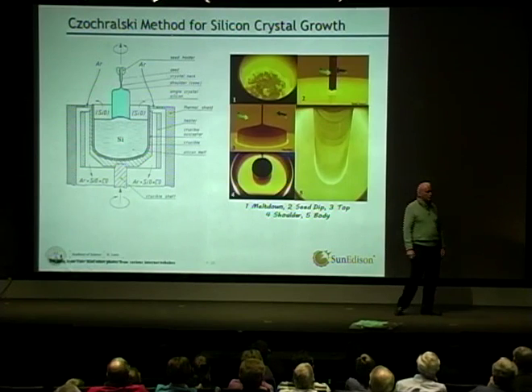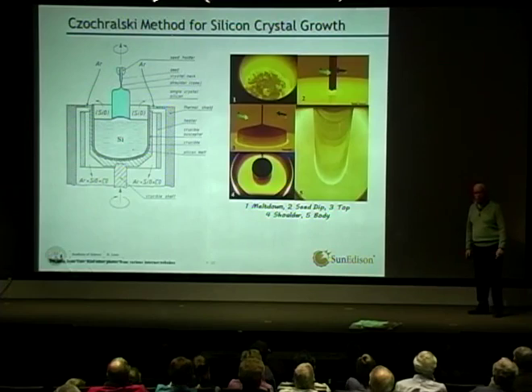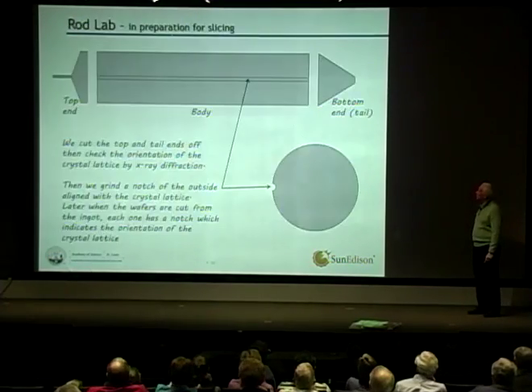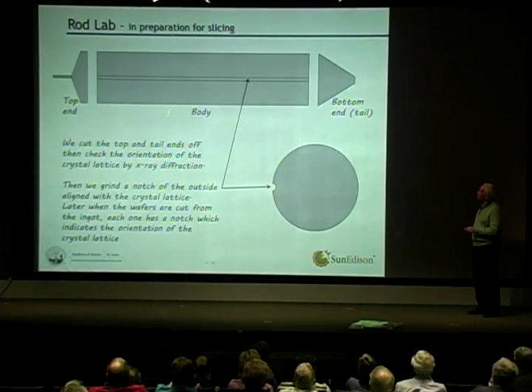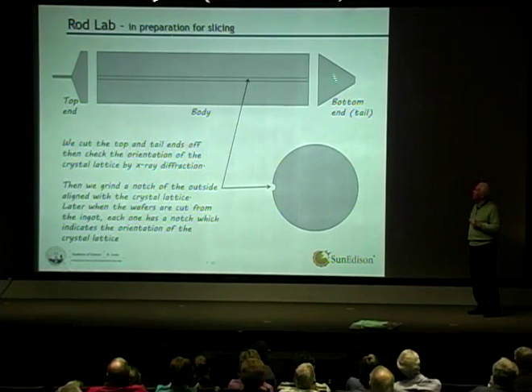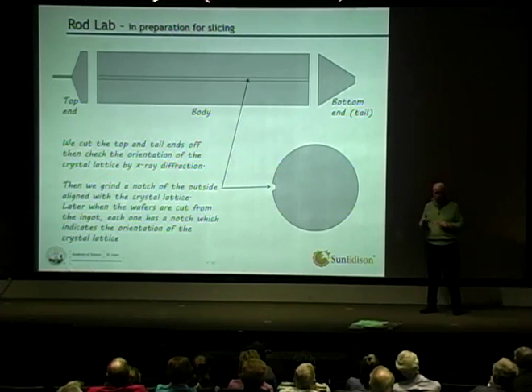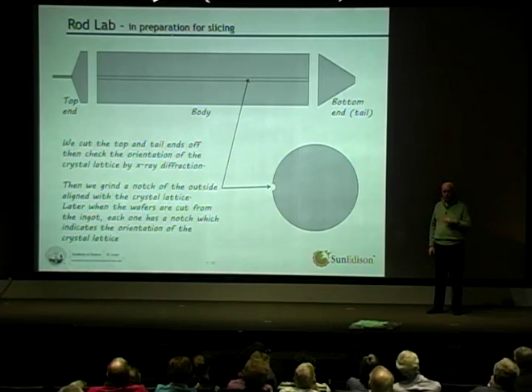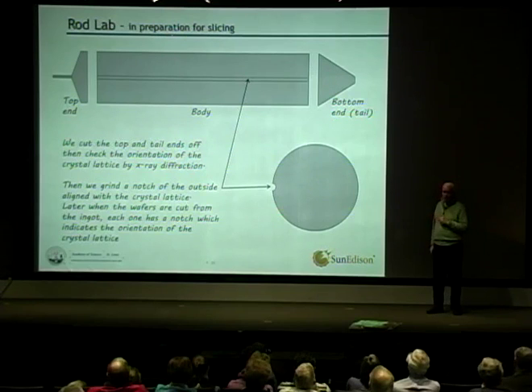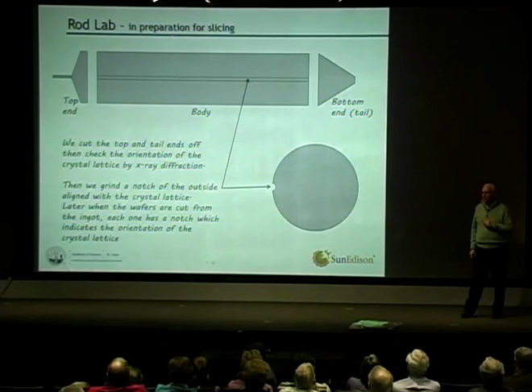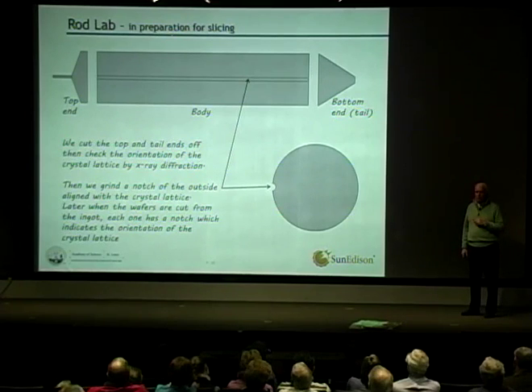Grant, you had a question? Grant's question is, what happens to the top and the tail part? The answer is that we do recycle. We cut the bottom off and the top, and we take that back and melt that down. And it turns out that this is actually purer than the original polysilicon. The reason is that when you're growing, the impurities prefer to stay in the liquid phase rather than the solid phase. So as you pull this out, when it becomes solid, most of the impurities are staying behind in the liquid. The solid is actually purer than the starting material. It's called segregation.